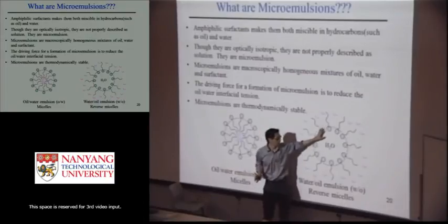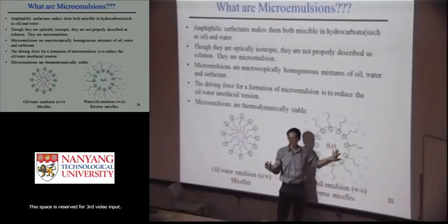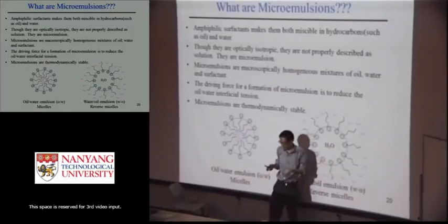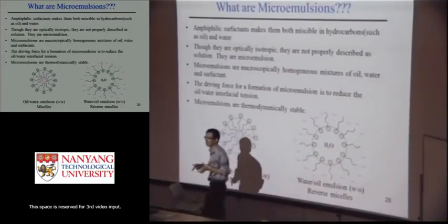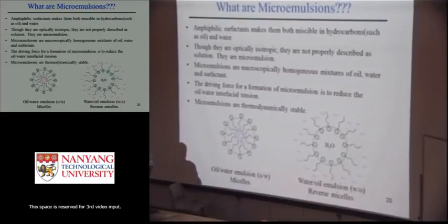Then those chemicals will be confined within this droplet and the chemical reaction will start within this droplet. Then this droplet is used as a so-called nanoreactor. So the reaction happens only within the droplet. If I control the droplet size to be, let's say, 5 nanometers, 10 nanometers, or even 50 nanometers, then the particle size will be confined by the droplet size.